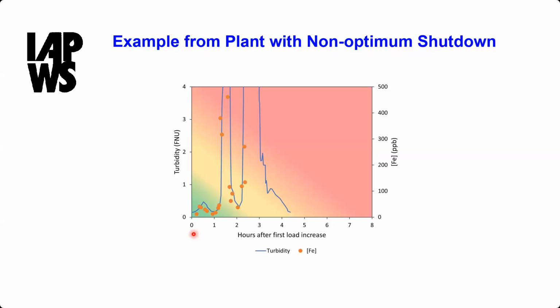And you contrast that by something like this. This is an example from a plant with non-optimum shutdown conditions. And here you can see that this trace is not in the green area and has a number of peaks like this. Each time the trace shows a peak like this, it means there's a high level of iron, as you can see over here, that's going to go into the unit and therefore increase the deposit.